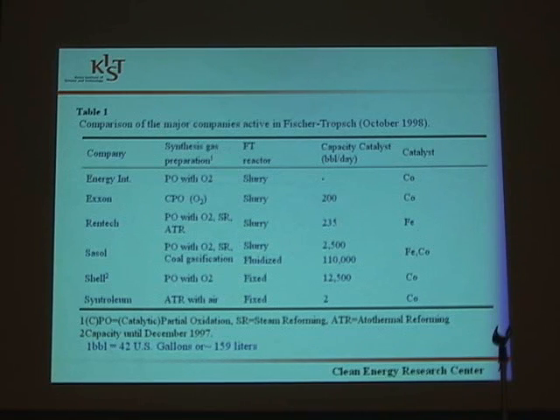Rentech uses partial oxidation with oxygen, steam reforming and autothermal reforming in a slurry reactor using iron-based catalyst. Sasol is using partial oxidation with oxygen, steam reforming, coal gasification, and they are using slurry as well as fluidized bed reactors and both iron as well as cobalt-based catalysts. Shell is preparing synthesis gas using partial oxidation with oxygen in a fixed bed reactor using cobalt-based catalyst. And Syntroleum is using autothermal reforming with air for the synthesis of syngas in a fixed bed reactor and cobalt as a catalyst.